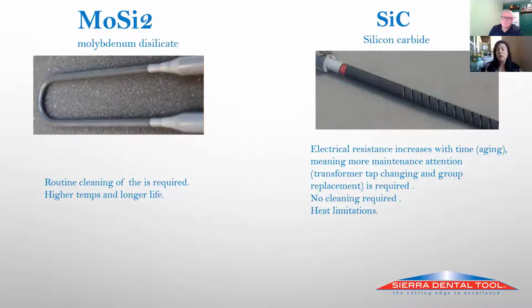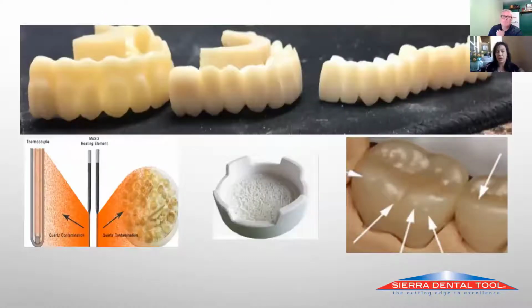So what you want to look for on a MoSi2 is almost like a calcification or a white, chalky, crystally buildup on the heating element itself. And those little particles, yes, exactly. So here on this slide, what's happening is the quartz that's building up on your MoSi2 will eventually fall off into your tray of beads. You're going to then put your crowns in those trays, and notice that you're getting perfect white dots.